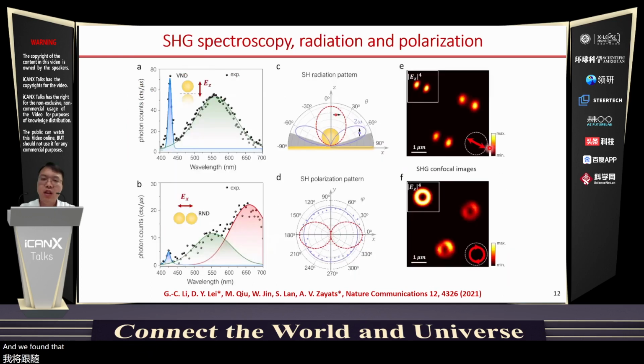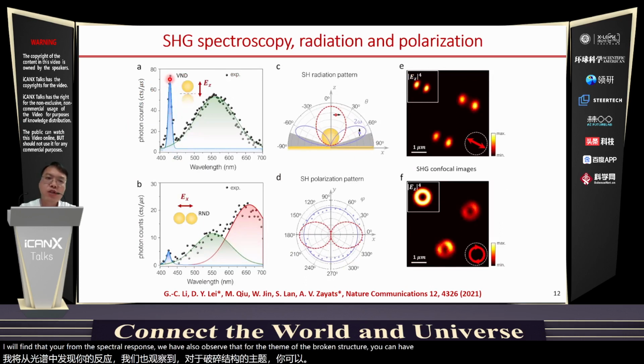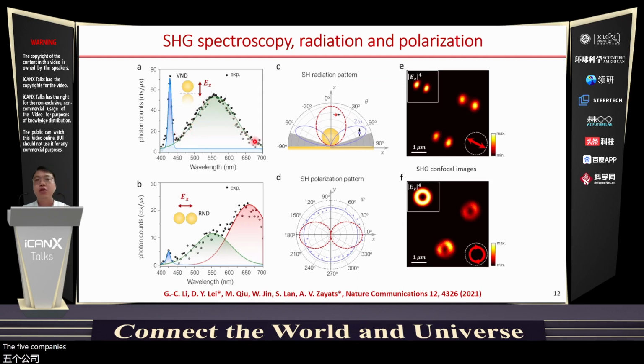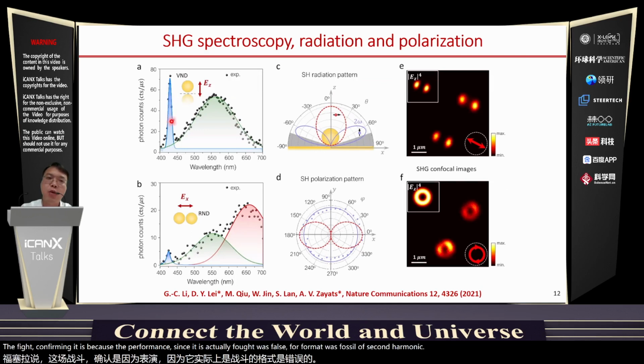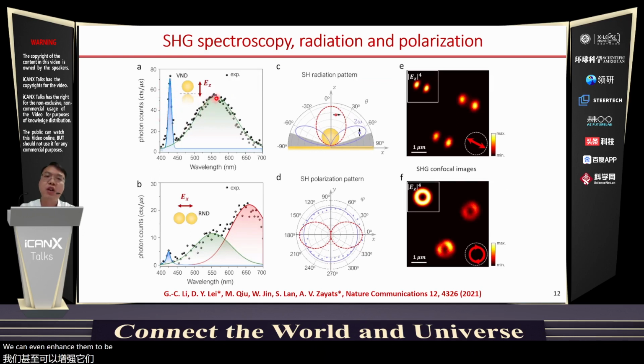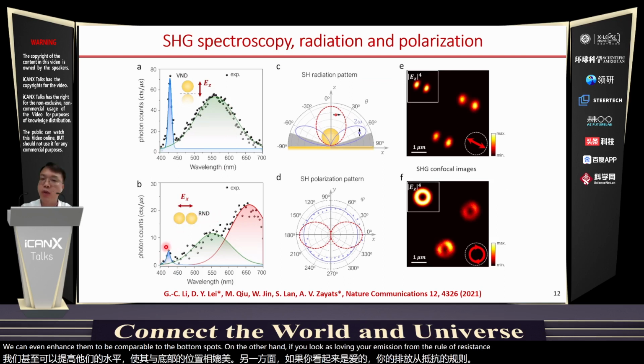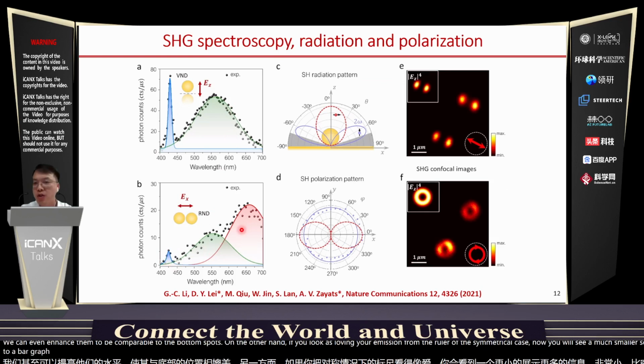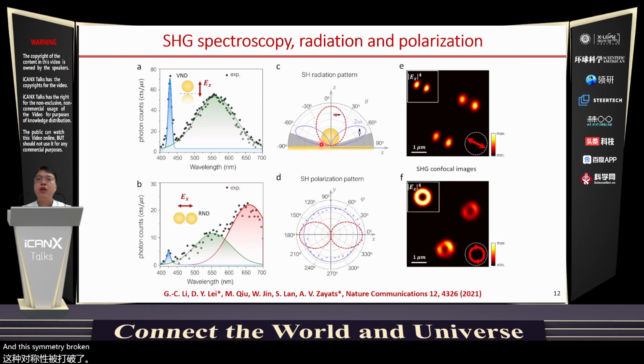And we found that from the spectral response, we have also observed that for the symmetry broken structure, we can have quite significant second harmonic emission signal, which is even comparable to the two-photon luminescence. That's quite counterintuitive, because the two-photon luminescence is actually a bulk response for metals, but the second harmonic response is a surface response. But now with such symmetry breaking argument, we can even enhance that to be comparable to the bulk response. On the other hand, if you look at the nonlinear emission from the real nanoparticle dimer, the symmetrical case, now you will see a much smaller second harmonic emission, much smaller than the bulk response. And this symmetry broken argument is also confirmed by measuring the second harmonic radiation pattern.